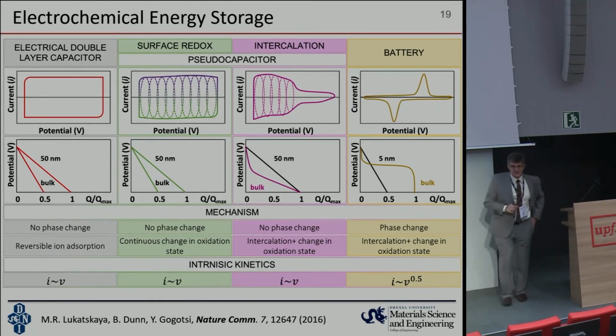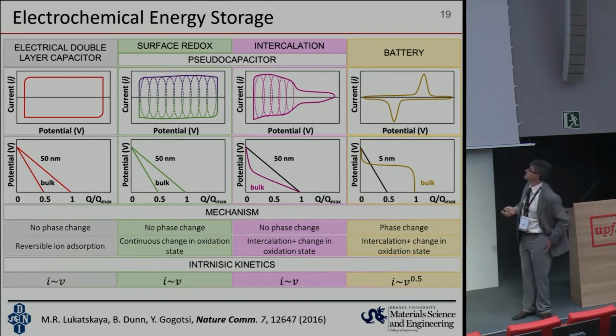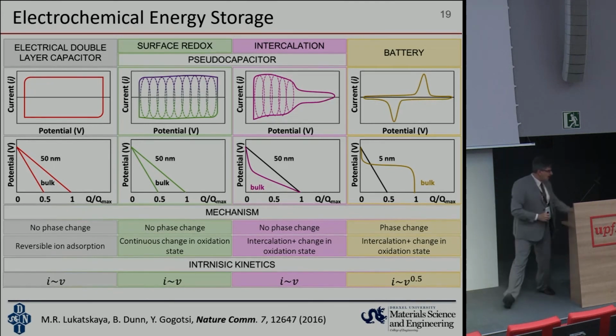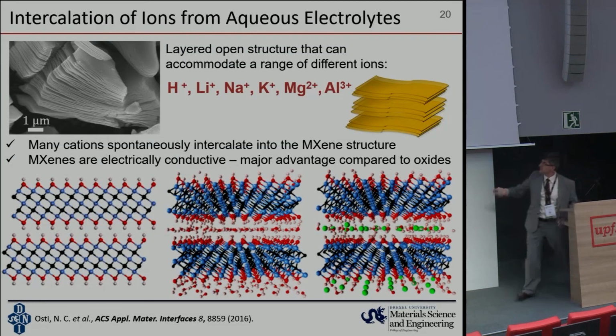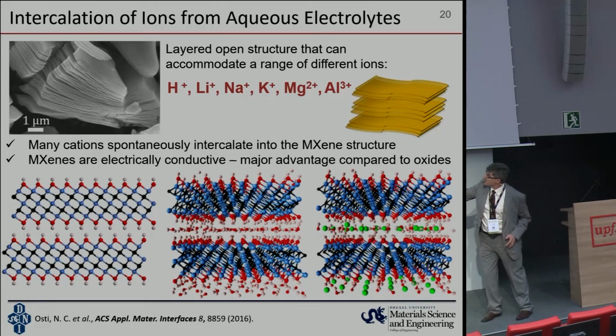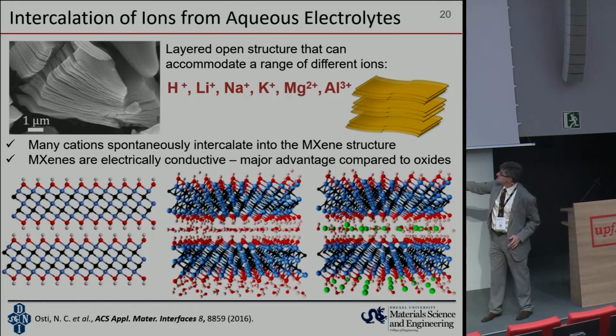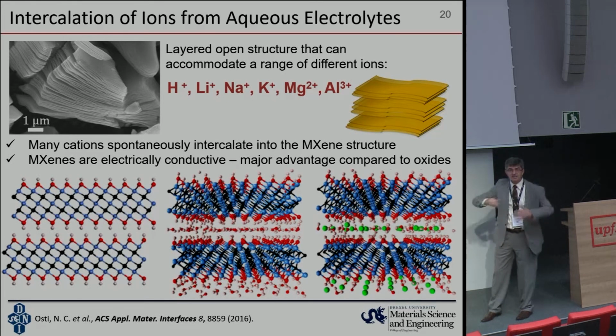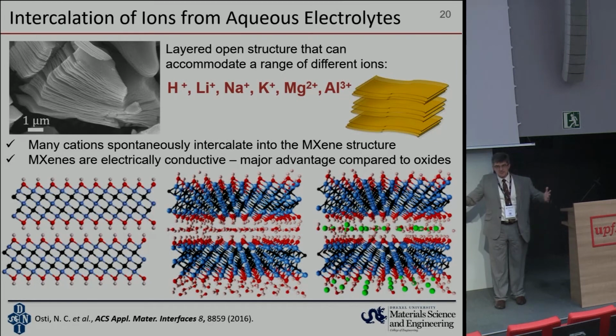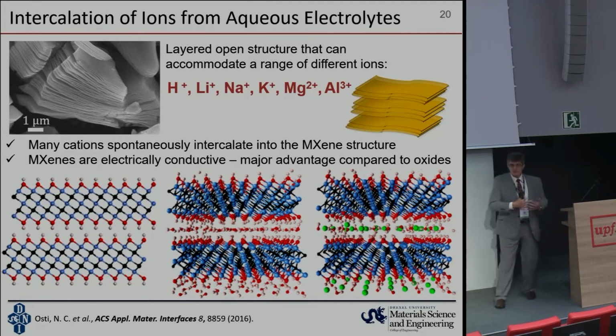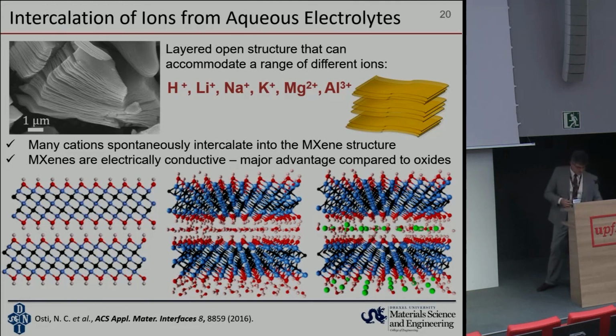And I'm running awfully late, as I see from the signs that the chairman showed. Unlike batteries, they're not limited by diffusional processes. And Patrice expanded a little on this, telling that double layer capacitors are great. They can be charged very quickly, but we also need redox capacitance to increase the energy density. And MXenes offer exactly this because they provide electrical conductivity with an inner layer, and they provide redox storage in the transition metal of the outer layer. So it's like an oxide on steroids. You can potentially have the same energy density because you can do the same redox reaction, but you have a metal, so you can also run electrons very, very quickly.